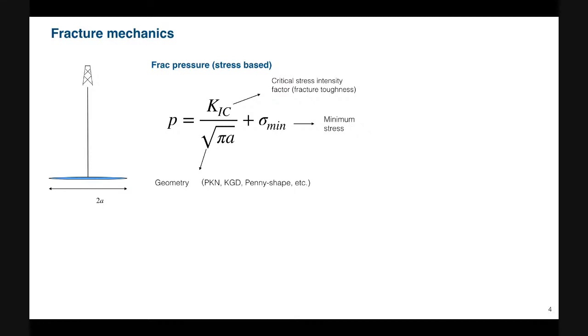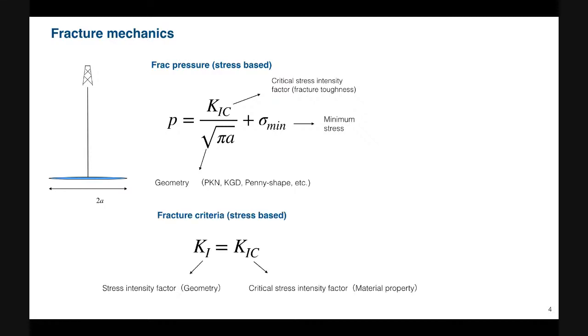For a simple geometry like this line crack, it's given by this expression, but for other geometries like PKN, KGD, and penny-shaped, there are different expressions. So formally, this is the criteria for fracture propagation. The left-hand side is a measure called stress intensity factor, computed based on the geometry. And on the right-hand side, we have the critical stress intensity factor, a material property, which is interchangeably called fracture toughness. For a line crack, the stress intensity factor is given by this expression.